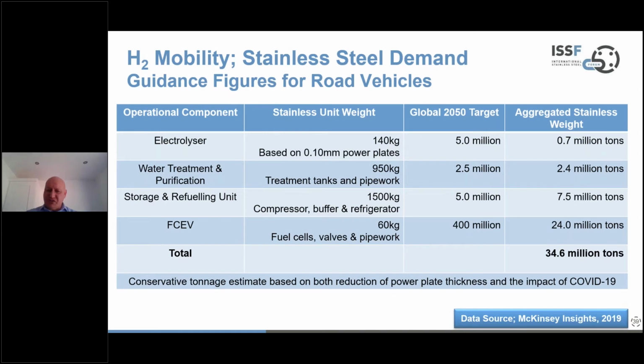Over 29 years, we're looking at almost 35 million tons of stainless, which is a little over 1 million tons a year, assuming a linear development, which of course we won't see. These estimates have been made a little bit more conservative, of the order of 15% conservative, to recognize that there could be a further reduction in power plate thickness and also the impact of recovery from the COVID-19 pandemic. So these are conservative estimates at this stage, but at least it gives some guidance numbers for people producing the assets and also supplying the materials.